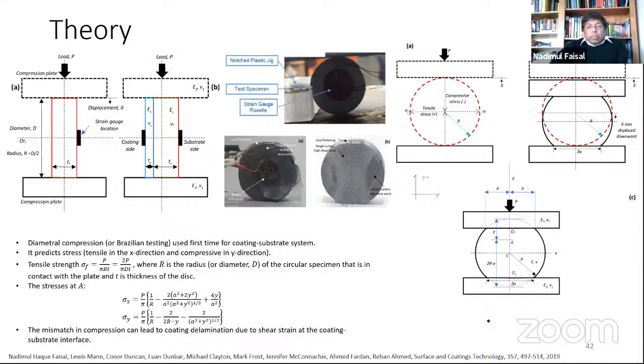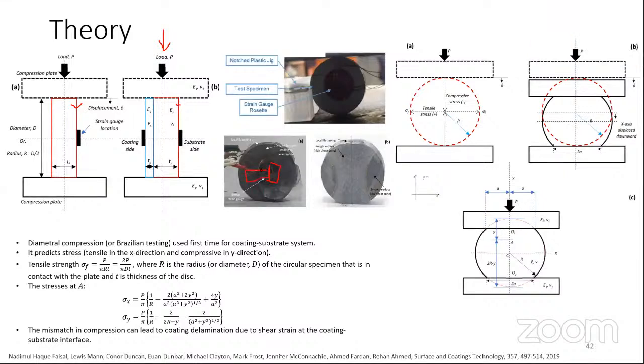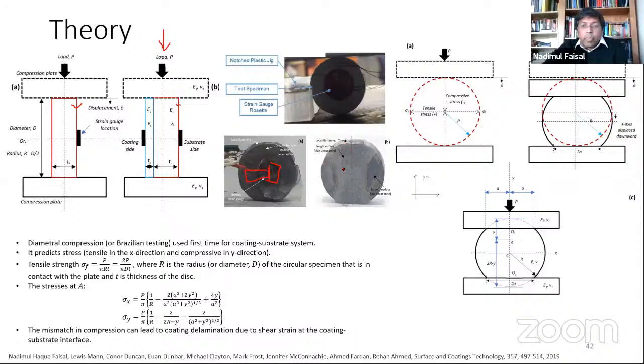All right, so the diametral compression method is used mainly in geomechanics to understand the tensile strength of geological samples. What we did in this case, we deployed a disk type sample. You can see here a substrate without coating, a substrate with coating. On one side it is coated, and you are applying a load on this. So this is a side view. If you see the front view, what we did, we put strain gauges in different directions, one direction and this direction, so that you can measure X and Y strain. And we applied a compressive load. Because of that, the coating came off, and before it came off, we measured a set of data about the strain. So you will find some fundamental theory, the equations involved. You can see all these strains in different directions.